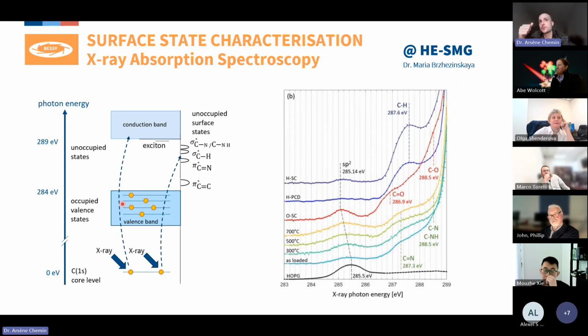And in that case, you would tend to have a more consistent negative charge on your NV centers. But you will have some trapping, etc., that can give you some more problems. This is why actually Alan developed the nitrogen terminated surface in the first place. Yeah, that's about it.